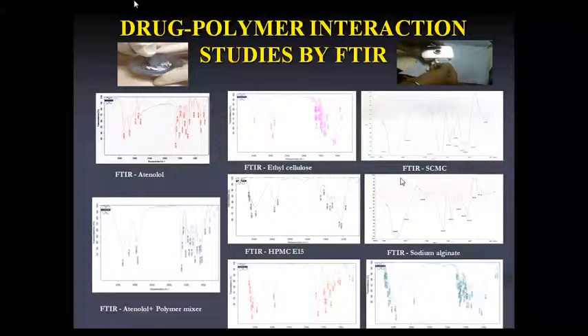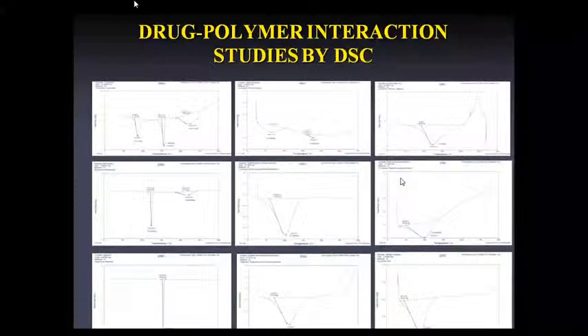All right. Then another study, which also comes under preliminary study, is the DSC, differential scanning calorimetry. Again, for the individual drug and polymers, and the drug and polymer together, you have to take the DSC thermogram and compare your sample with the standard sample. If there are no changes in the thermogram, then you can confirm that the drug and the polymer are not chemically incompatible, so you can choose this drug and polymer for further formulation steps. So these are the 3 preliminary studies we need to know for selection of your drugs and polymers.